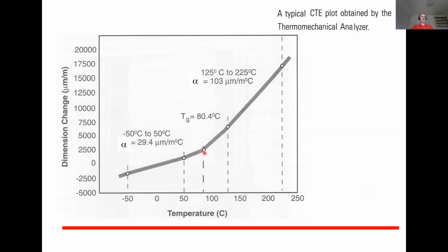So we try to typically stay below the Tg, so that in the use conditions we don't go into this area, because then the epoxy would expand much and of course stress the other materials which it is attached to. And the other important thing is, even though it is said that the Tg is 80.4 degrees centigrade,